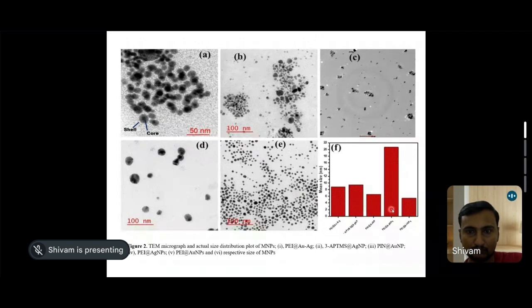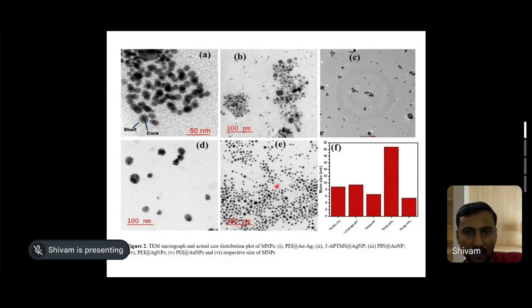So the mean size of the PEI-stabilized gold-silver nanoparticle was high, around 22 nanometer in actual size, not hydrodynamic radii. Hydrodynamic radii is a different thing and actual size is a different parameter. However, the polyethylenimine-stabilized gold nanoparticle was below 10 nanometer, around 6 nanometer in size.